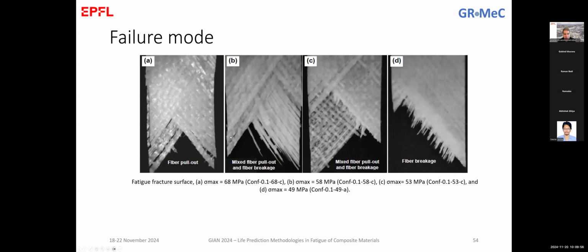So the failure modes were different for different stress levels. And what is shown here is that for higher stress levels, what you see on the left in figure A, photo A, is that we had more fiber pull-out. It was a bit of a mix of fiber pull-out and fiber breakage at intermediate stress levels, and it was more fiber breakage at low stress levels.